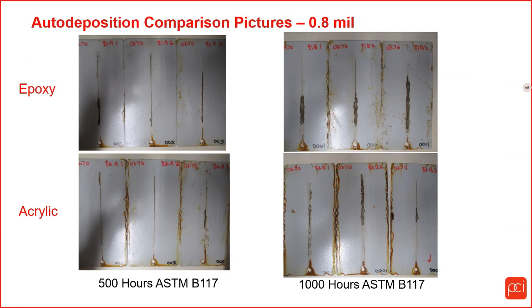These are the 0.8 mil pictures. You can see a little bit of difference in the 500 hour salt spray. Epoxy did slightly worse than the acrylic. And then on the 1,000 hour salt spray, you can see that the epoxy had greater creep than what the acrylic did.